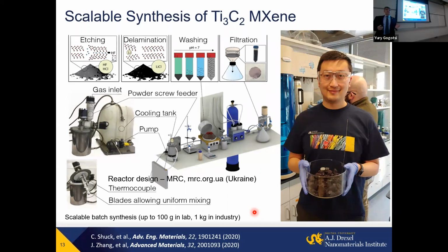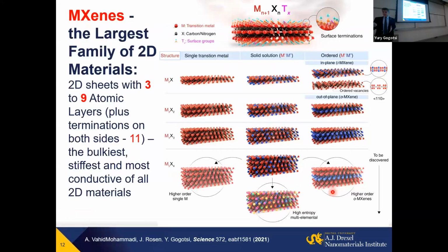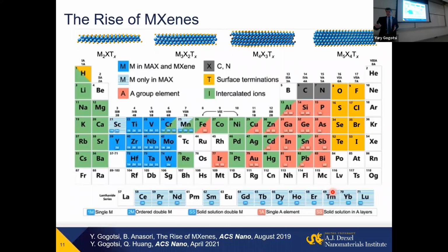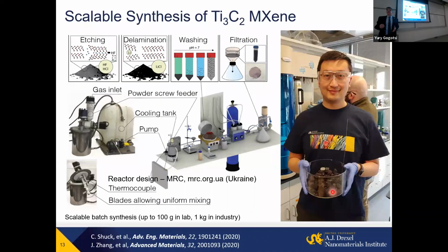We, from the very beginning, were making this material in large quantities, because we take ceramic powder and dump it into a reactor. Actually, this was designed by a small Ukrainian company for us. Here, get MXene, delaminate it, wash it, and produce the material. Here is my postdoc, John Jung, holding 1 kilogram of MXene. Sorry, pushing wrong buttons again. 1 kilogram of 2D material.